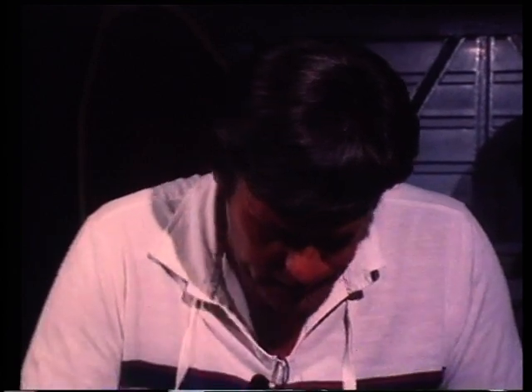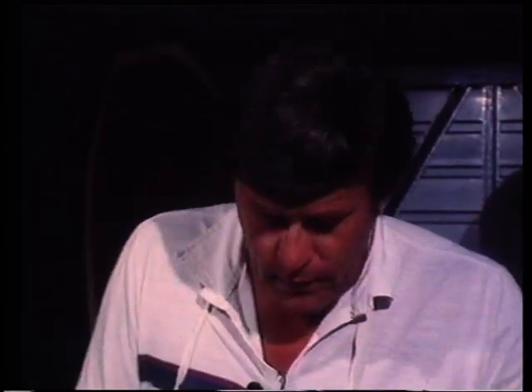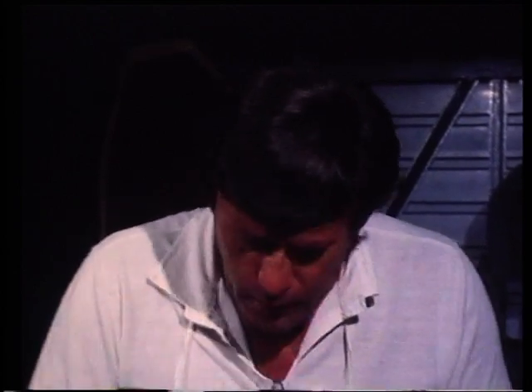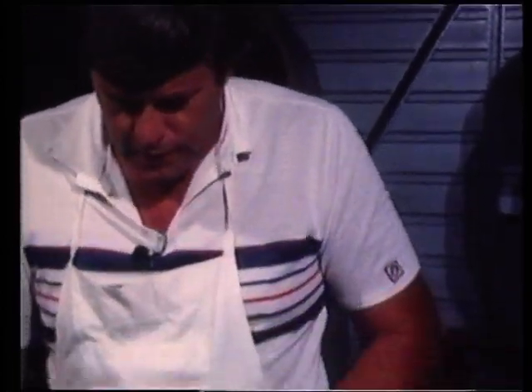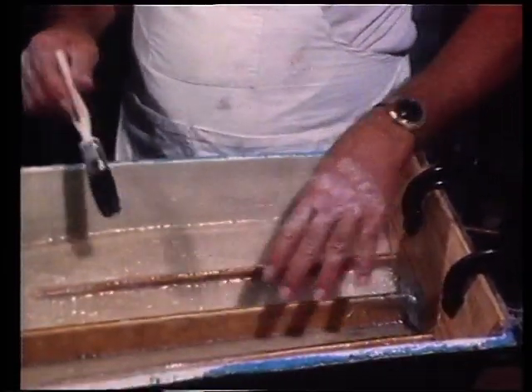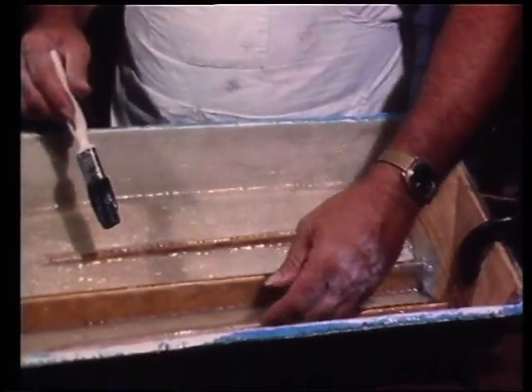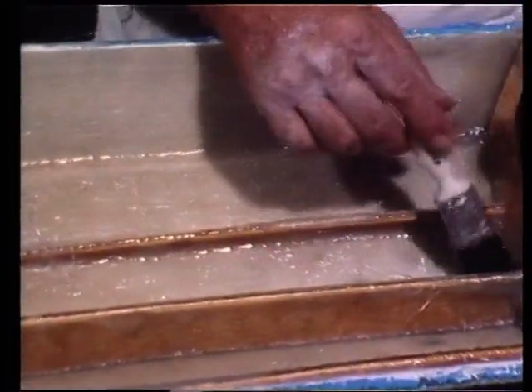Right, well, we've allowed the laminate holding the stringers and the transom into the boat to gel, and I've applied the laminate over the top of the stringers here. Now, the interesting thing about that is that you're applying another layer to the inside of the boat when you do that. So that means that you allow for that when you're calculating the total number of layers that you put in the boat.